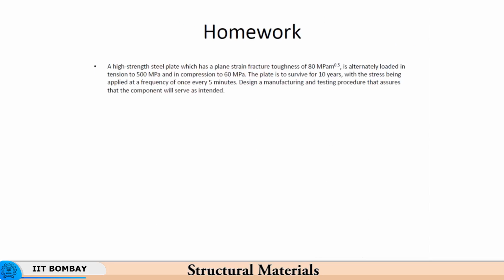So, now we take up a small problem which you can solve at home, and then we will also give out the solution to that. A high strength steel plate which has a plane strain fracture toughness of 80 MPa meter raised to 0.5 is alternately loaded in tension to 500 MPa and compression to 60 MPa. So, now you see that the loading is not symmetric between tension and compression. It is more in the tension region, it is less in the compression region, but nevertheless it does get into the compressive regime. So, the plate is to survive for 10 years. So, the life of the plate you expect is 10 years, and it is being subjected to this kind of fatigue, 500 MPa in tension and 60 MPa in compression.